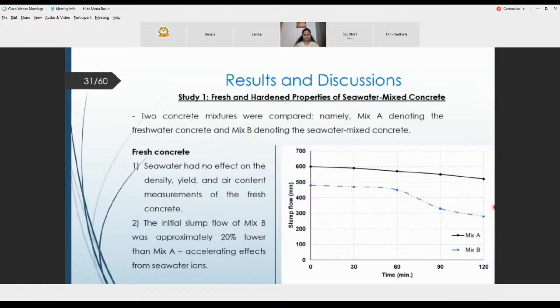You can see from this relationship between slump flow on the vertical axis and time that mix B was approximately 20% lower than mix A in terms of the initial slump flow value.